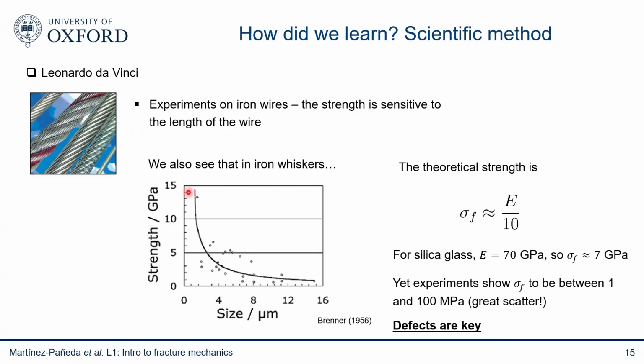And in fact, nowadays we can predict, either using atomistics or even theoretical considerations, the theoretical strength of materials. And we roughly know that it's the Young's modulus divided by 10. So for silica glass, which is a model material, and we'll discuss it later on, we have a Young's modulus of 70 gigapascals, so a failure strength of 7 gigapascals. However, when we do experiments in the lab, we show that the failure stress, the strength of silica glass, varies between 1 and 100 megapascals. So lots of scatter, and also much lower than what we expect from theoretical considerations.